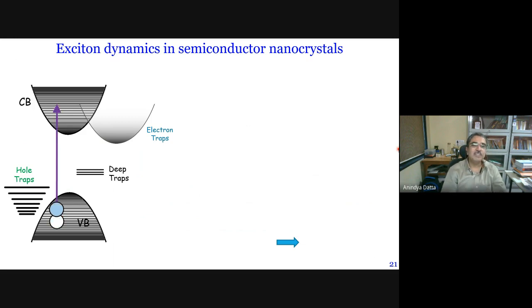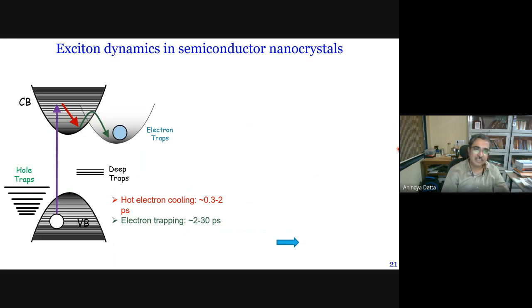So first of all, when we excite, this much I think is something that all of us know, we create an exciton where we have an electron in the conduction band, a hole in the valence band, and they're coupled. Now, we typically excite at energies that are beyond the band gap. So, you create hot electrons and hot holes, so they can cool down. That time is typically associated with 0.3 to 2 picoseconds. Then electrons can get trapped. Typically, from literature, we know that that time can range from 2 to 30 picosecond.